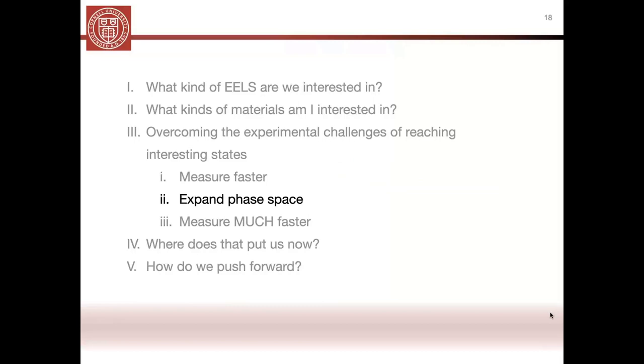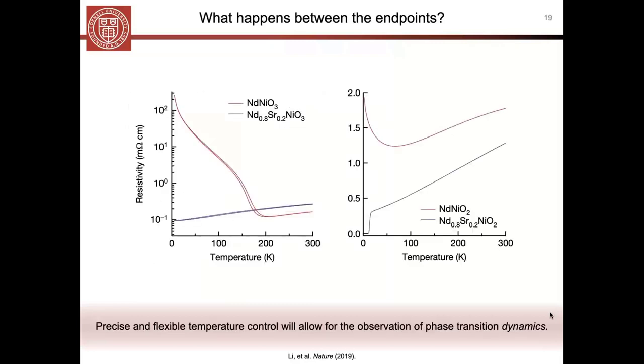Now, the next thing that we want to do is we want to actually measure not just at room temperature and at cryogenic, the temperature of our cryogen, but we actually want to measure across that whole temperature range. So again, if we go back to, for instance, these transport plots that I showed you earlier, of a perovskite phase or an infinite layer phase, and these are just kind of stand-ins, pick your favorite oxide material and plot the transport as a function of temperature, you'll get some sort of interesting trace. If we use these as an example, at 300 K, this is the temperature where we usually measure. And now with a liquid nitrogen cryoholder, we have access to these lower temperatures, just under 100 Kelvin. And so here in the perovskite, you can see that now we have access to this other phase.